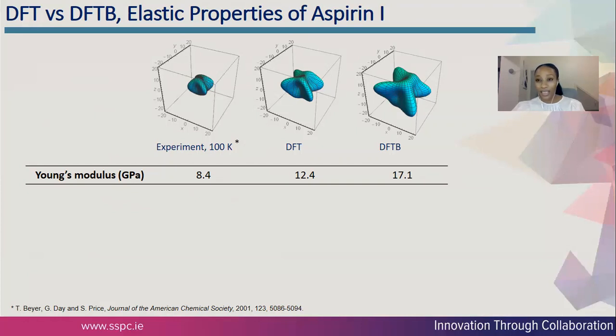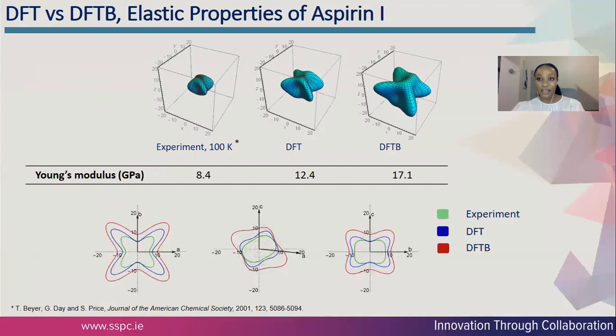To further explore this qualitative agreement, we can take a slice of the 3D object of the Young's modulus in different directions or planes to give a 2D spatial dependence of the Young's modulus. So I've taken a slice in the AB, AC, and BC crystallographic planes, as shown by the 2D plots here on the bottom panel. From this, we can see that the two computational methods qualitatively agree with experiment, with slight discrepancies.